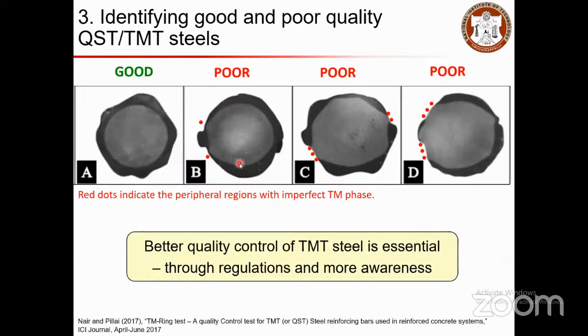Whereas here, this is an example of a poor quality rebar. The ring is not uniform or consistent around. Here you can see the thickness of the ring is less. Here again you can see there is no TM at all, and here you can see the same scenario. The red dots indicate the peripheral regions with imperfect TM phase. Better quality control of TM bars is essential through regulations and more awareness. Professor Pillai extensively works on TMT quality assurance testing. A test method is also proposed based on the same TM ring test, as a quality control test for TMT bars.